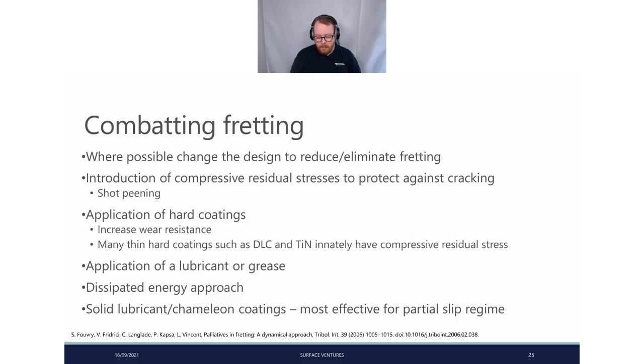So hydrogenated amorphous carbon would probably be the type of DLC that would perform best. It has a high H over E ratio. It is lubricious. You will form a tribo layer in that it will graphitize. So yes, you are going to form wear particles, but they're going to be helpful in your contact, and it has a lower coefficient of friction than some of the harder DLCs. Application of a lubricant or grease. I'll go into this a little bit more later.